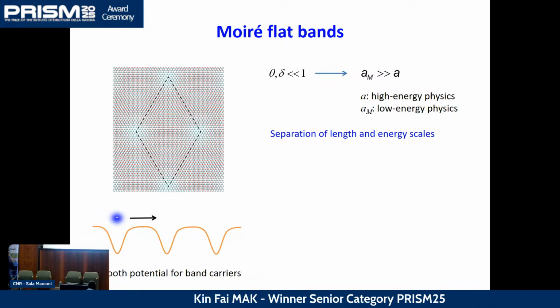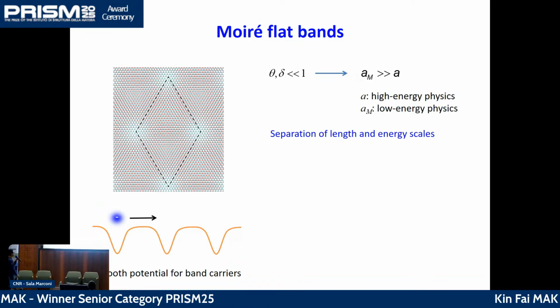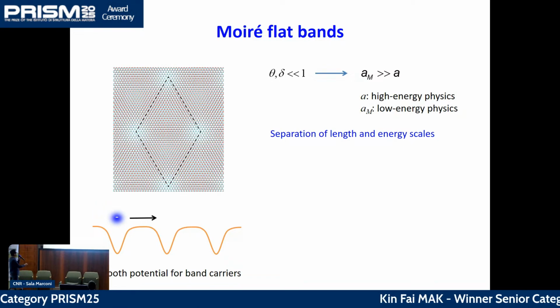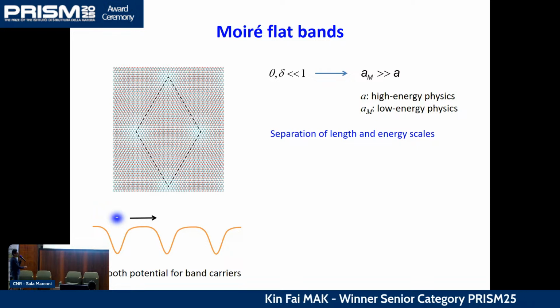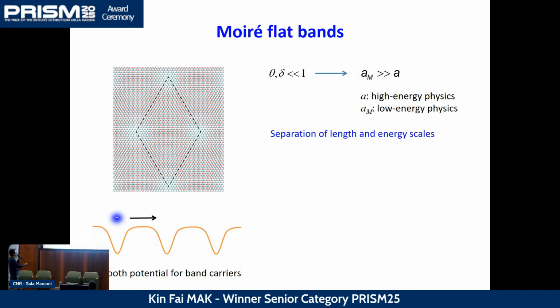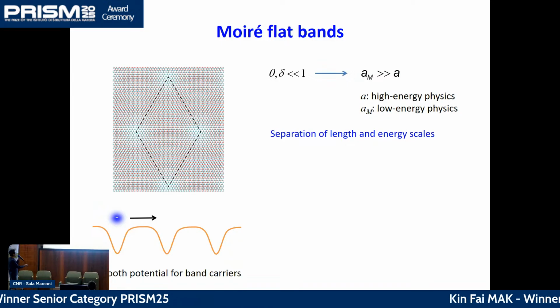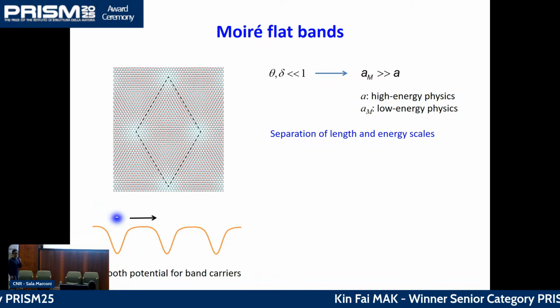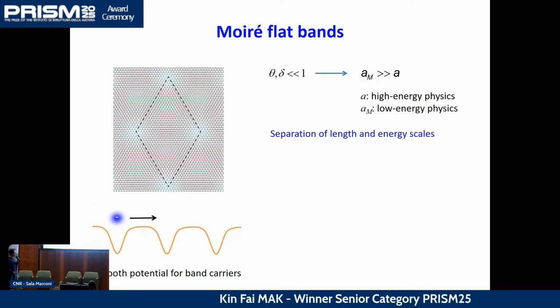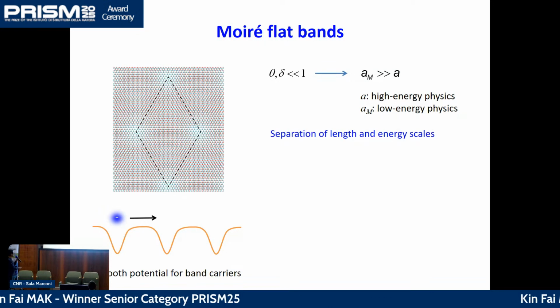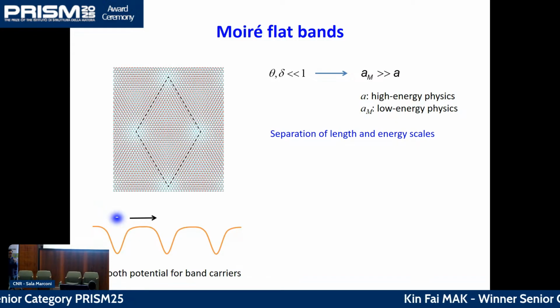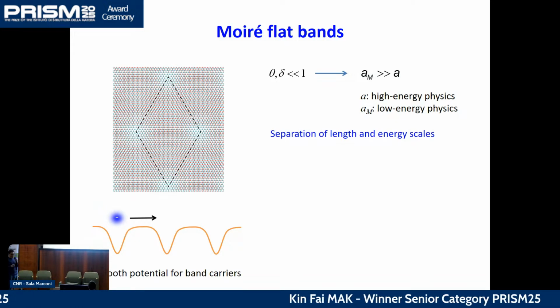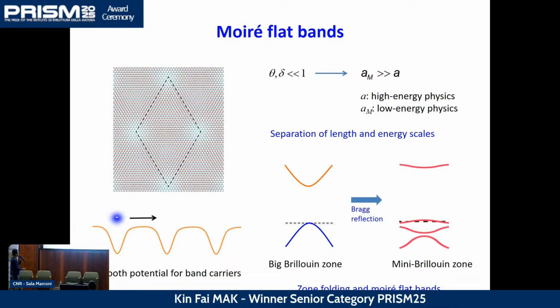Okay, so now let me highlight a few of the generic properties with this emergence of a new superlattice structure. First of all, in this limit, it's particularly easy to deal with the physics. As long as we're talking about very small twist angle or very small lattice mismatch, the moire period is much longer than the original lattice constant. So to a very good approximation, we can forget about the original lattice and just treat the electrons as moving in a smooth periodic potential defined by this moire lattice. Okay, so we can forget about the atoms completely. And the effect of that is the following.